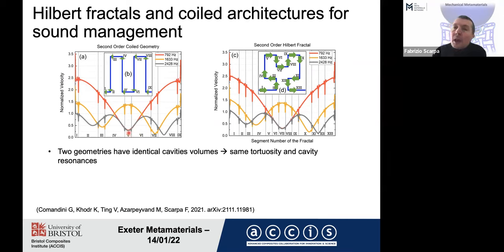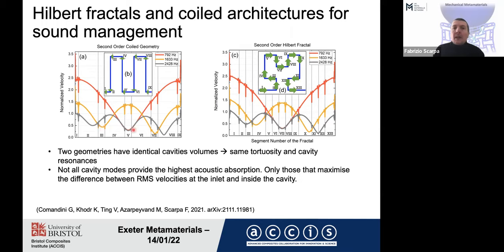So for example, if you look at the absorption coefficient, you will tend to have peak absorption at that frequency at 792 Hertz, and then also peak absorption at that frequency at 1600 Hertz, but not at another frequency corresponding to that peak. So this is quite important. It actually provides a guideline on how to design this fractal or tortuous type of metamaterials for acoustics.